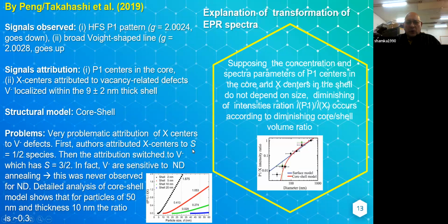When you start analyzing the core shell model more carefully, you can see that, in fact, core shell provides very different numbers, for example, for a 50 nanometer particle, which doesn't correspond to their spectrum. According to the pure core shell model, in 50 nanometer particles you have to see quite a strong P1 signal. They don't see it. They see maybe 1/10 of this signal. It gives us a hint that something is bad with this explanation.